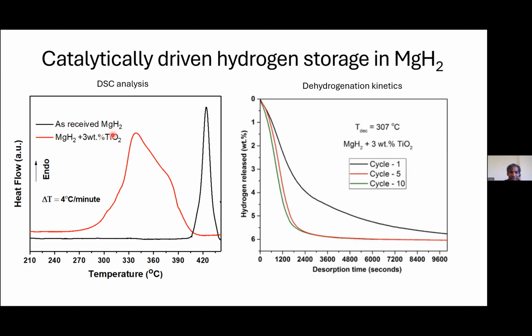A 3-weight percentage of titanium dioxide was incorporated with magnesium hydride through mechanical milling treatment, and the experiments were done then under identical conditions. Then what happened? You see this in the results. The dehydrogenation temperature decreased dramatically, by almost 100 degrees centigrade, even more than 100 degrees centigrade. It's very interesting. That gives you tremendous economic benefits.